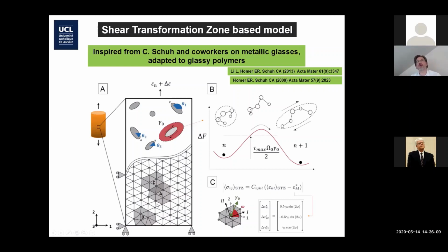The idea of Schuh and his group was to use the finite element method to solve the elasticity problem. So basically, it's an elastic problem interacting with a UMAT that takes care of the triggering and activation of the STZ. In order to do that, you create a finite element mesh. You decide what will be the size of your possible STZ. You provide to every element a certain energy barrier and some parameters I will describe next. And then at every increment of the calculation, you go over all elements and you check whether or not one element or one group of elements should be transformed because it has attained the criteria for triggering an STZ. And the finite element formulation takes into account the redistribution of stress using an elastic framework.